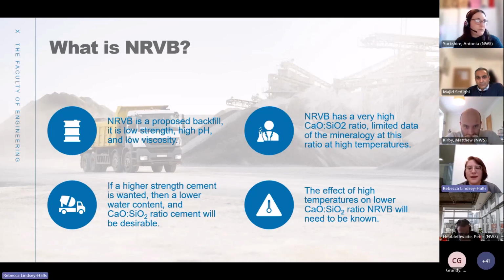NRVB has a very high calcium oxide to silicon dioxide ratio, about 7.27. There's limited data on the mineralogy that forms at these high ratios, and particularly at these high ratios at high temperatures. And if ultimately a higher strength cement is wanted, one of the ways it's done in industry to increase the strength of cements is to add more silicon dioxide, reducing the ratio. So looking at this lower ratio cement at higher temperatures is also useful to do.